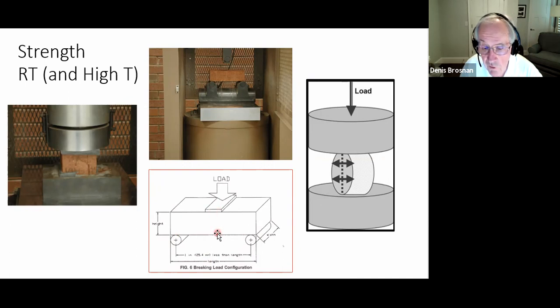And that surface that's in tension is the lower surface. I hope I said that right previously in the lecture. The ceramic is trying to bend or deflect because of this load in the center, and that forms a tensile stress in the bottom of the ceramic, the lower surface of the ceramic part. If you use a calculation, then you can calculate that maximum tensile stress or fiber stress in the ceramic at failure, and that's called the modulus of rupture, the typical failure in bending.